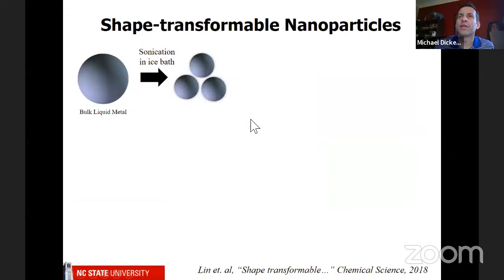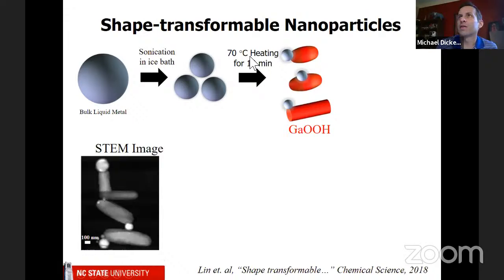So what we did is we took the bulk liquid metal, sonicated it, but did it at low temperatures to make sure, because sonication can kind of make the solution hot. So we sonicated it in an ice bath, and we actually got spheres. We then took those spheres and we heated them up at 70 degrees for 1 minute. And we find that we actually form gallium oxide monohydroxide, so GaOOH.